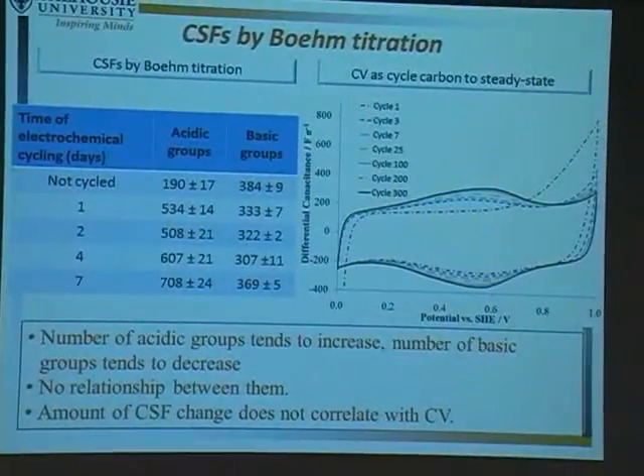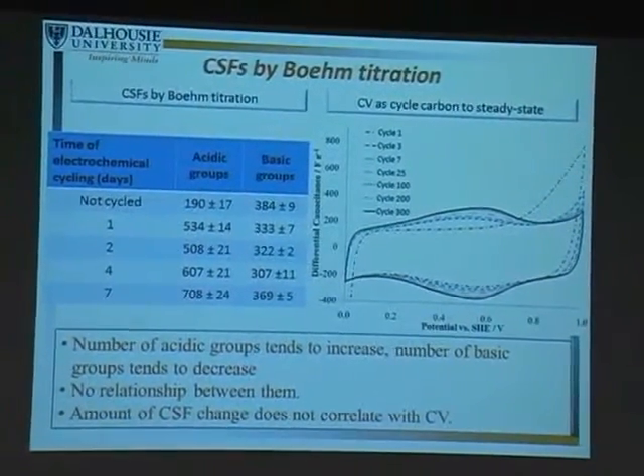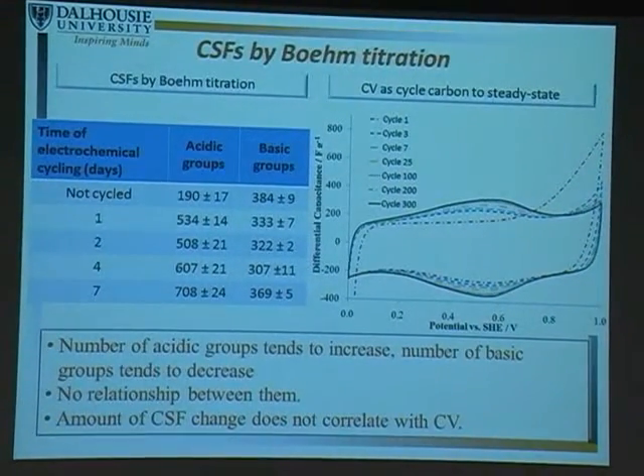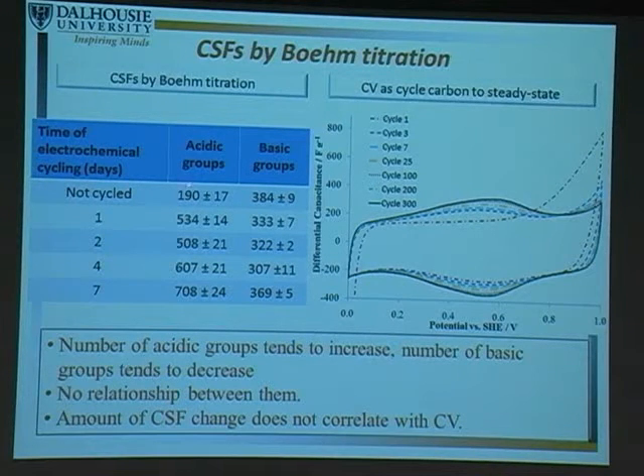And we were very hopeful for the Boehm titration. This is sort of the standard for chemists. If we want to look at surface functionalities, the Boehm titration is the way to go. And so we did this, and originally we were very excited, we saw the basic groups appeared to be decreasing, and then all of a sudden they increased at the end. This is exactly opposite to what we might expect, and in fact, there's really no trend here. The acidic groups did a very similar thing. We thought they were increasing, then they dropped, then they increased again.